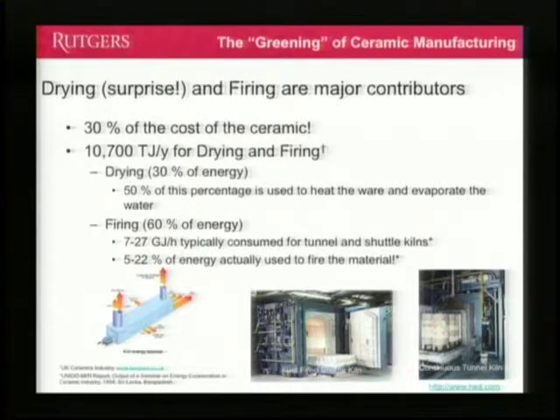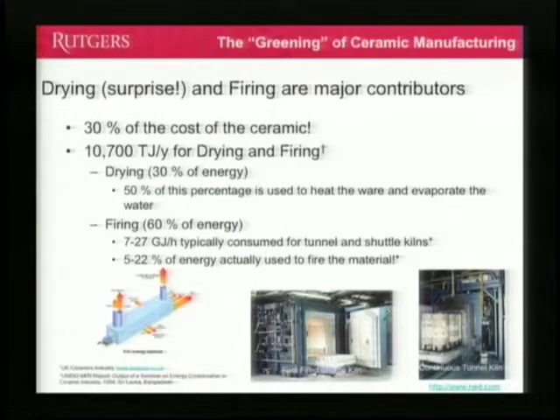30% of that energy that I'm mentioning here is spent drying, and it only takes double that for firing. That's the reason why, even though drying is a low temperature process, the length of time required in drying is so much longer than a firing step that your energy consumption can in fact be comparable. And these are some of the numbers of energy that you might consume per hour, on the order of gigajoules. And when you're doing this process, maybe if you're lucky, 20% of the energy is actually going for the process you're trying to heat.